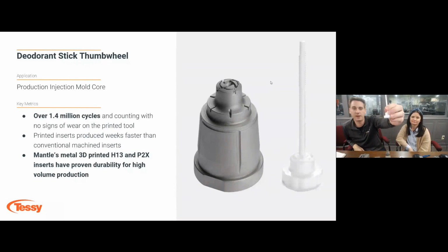What Tessie wanted to do was evaluate the durability of Mantle's material through a study. They took 3 of the inserts out of the tool, 3 of the 32. They printed 1 in Mantle's H13 tool steel, 1 in Mantle's P2X tool steel, and had 1 freshly machined out of S7. The tool has been running since February of 2021 and has experienced over 1.4 million cycles and counting. That could be closer to 1.5 million cycles because it's running as we speak, and they've seen no signs of wear on this printed tool, which is especially significant since this has a lot of shutoffs on it, which is actually being shut off with S7, and they have seen no signs of galling, wear, or any flash on the parts. So this was a great example speaking to the durability of Mantle's tools, and that they are true production tools.